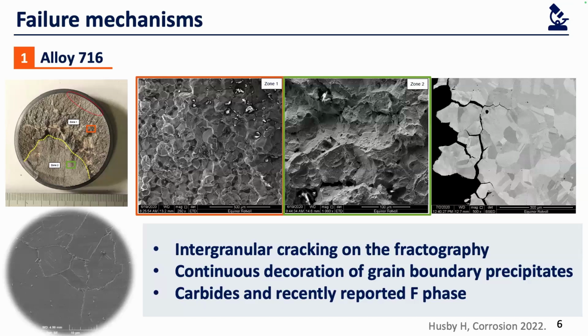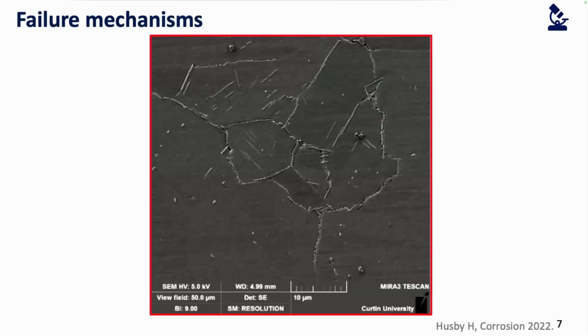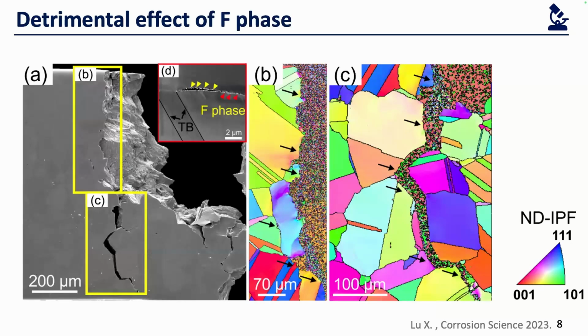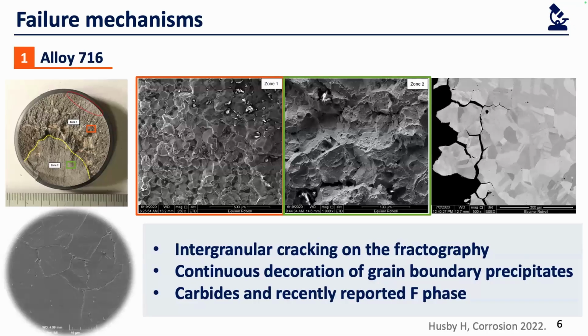Now we can take a look at the failure mechanisms of the reported failed components. This one is alloy 716. This figure I think you already saw in Professor Jianying He's presentation. Then we took a look at zone 1 and zone 2, and we see a clear intergranular fracture of this failed fastener. Further investigation reveals total intergranular fracture. That means intergranular cracking is the main reason for the failure of this fastener. If we take a close look at the microstructure, we can see along the grain boundary many precipitates are present. Some of them are continuous along the grain boundary, and some of them are acicular in shape. These precipitates are carbides and, as recently reported F phase based on the results from XRD.